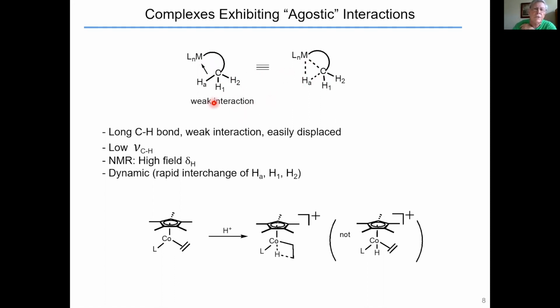These agostic species exhibit long CH bonds. It's a weak interaction. That CH interaction is easily displaced. The CH frequency is low. In the NMR spectrum, typically the CH bond exhibits a high field chemical shift. And since this is a weak interaction, these are highly dynamic. So there's rapid exchange between HA, H1, and H2. An example here that I'll show you more about later comes from simply the protonation of a cobalt ethylene complex, this cobalt-1 species, to generate an ethyl agostic species in which the beta CH is bridged back to the cobalt center. It's not an ethylene hydride, but an agostic species.